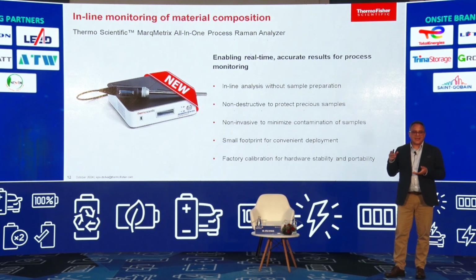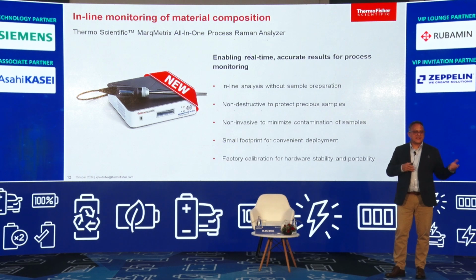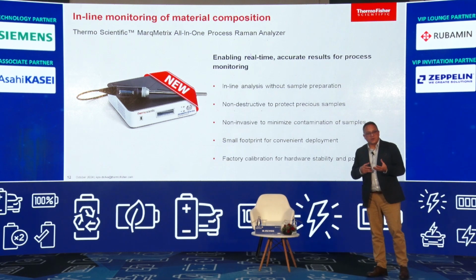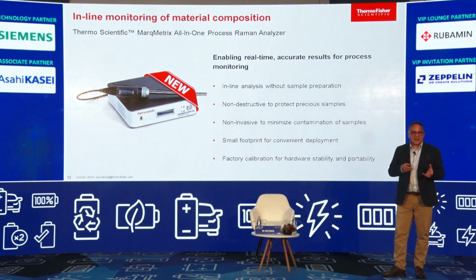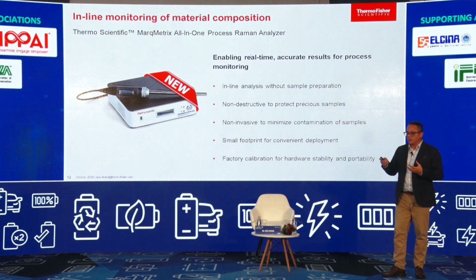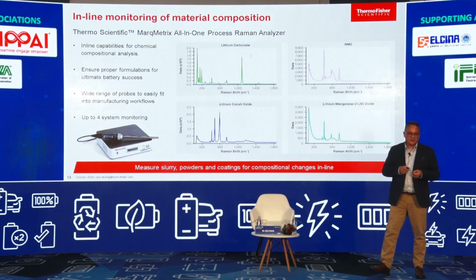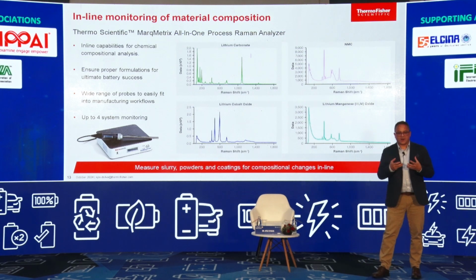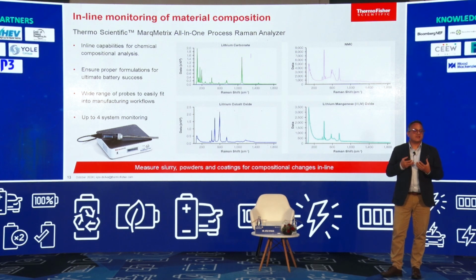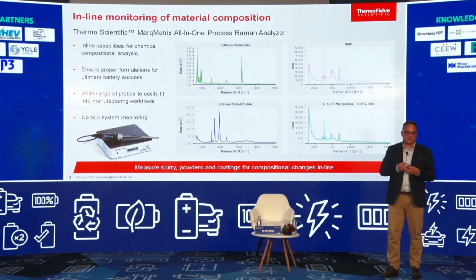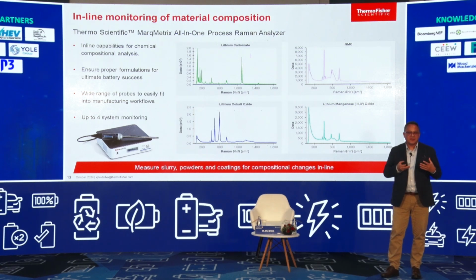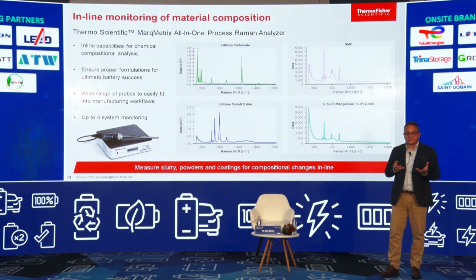What does it give you? Inline, continuous monitoring of the composition of the sample. It doesn't require any sampling. It doesn't contaminate the sample, and it's non-destructive. So it allows you to continuously monitor with high degrees of confidence. It generates Raman spectra that give a unique fingerprint to each material or each mixture of materials. We can measure the fingerprints to calculate the concentration of each sample.